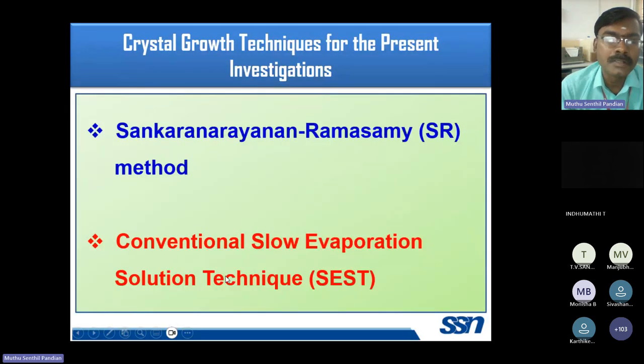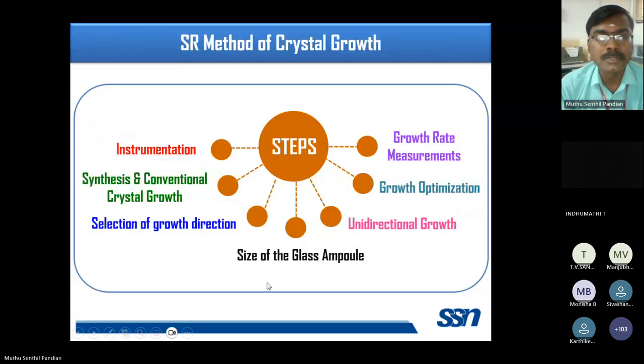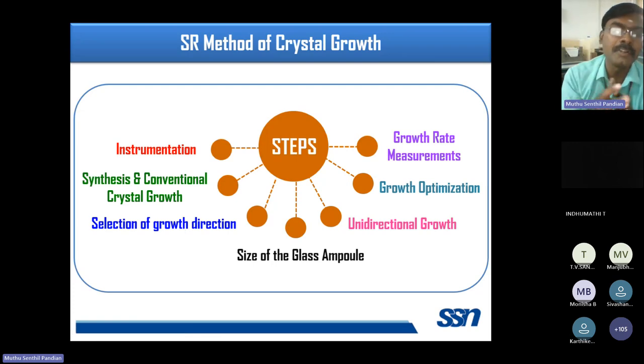So the crystal growth techniques for the present investigation, I mainly concentrated on these two different methods, the Sankaranarayanan-Ramasamy method and the conventional slow evaporation method. To grow the crystal by this Sankaranarayanan-Ramasamy method, we have to carefully optimize all these parameters like instrumentation, synthesis and conventional crystal growth, and different seed crystal directions, whether we wish to grow the crystal along its a direction, b direction, c direction, or if it is a non-ferroelectric symmetric material, we have to identify the phase matching direction, or if it is a ferroelectric material, we have to identify the polar b direction, and we have to grow the crystal along its polar b direction by this SR method.